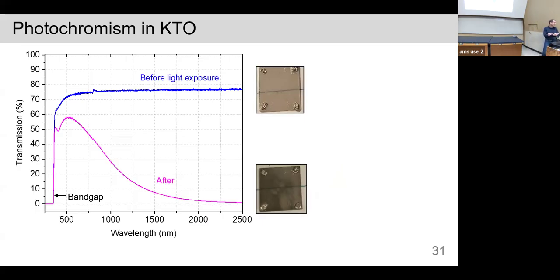So going back to potassium tantalate, before light exposure, Macarena measured the transmission spectrum. Here's the bandgap absorption right here. The transmission drops right where it should. And it's pretty flat. This is just an artifact here. It's pretty flat over a wide range. But after light exposure, remember we get lots of conduction. This low transmission at long wavelengths is due to free carrier absorption. However, in addition, there's a dip right at 400 nanometers. And that is attributed to some defect, which I think is iron, but we're not sure. That is changing its charge state and then becoming optically active, and now has this peak. So it's a signature, if you will.